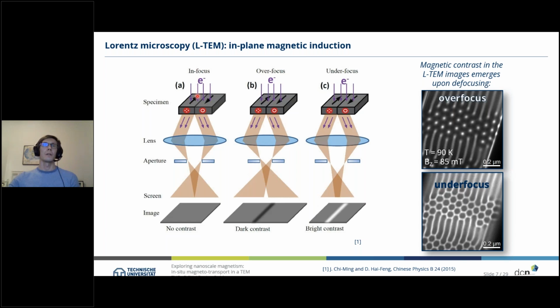on where you are in the sample, on the domain. And that leads then to a contrast if you go to either overfocus as a dark contrast at the location of the domain wall, and in underfocus as a bright contrast in the image. And in reality, this is shown here on the right-hand side, an experiment performed on iron germanium, a material which also shows a skyrmion lattice. And you can see that in overfocus, the skyrmion pops up as a bright point, whereas in underfocus, we see that the skyrmion shows a black contrast with a hexagonal pattern arrangement.